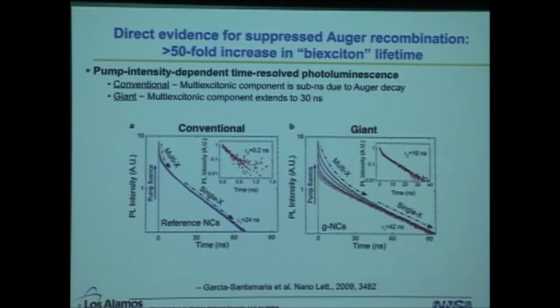And that's all about blinking, which could conceivably be a surface charge effect only because we have a thick shell. As I mentioned, we're protecting the excitonic wave function and so on. So do we have evidence to suggest that we've done something more than that? And specifically with respect to Auger recombination and suppression of Auger. And indeed we do. This is collaborative work done with a group out of the chemistry division. I'm actually now in materials physics and applications. And they use pump intensity dependent time resolved PL to demonstrate, at least indirectly, that Auger is suppressed.